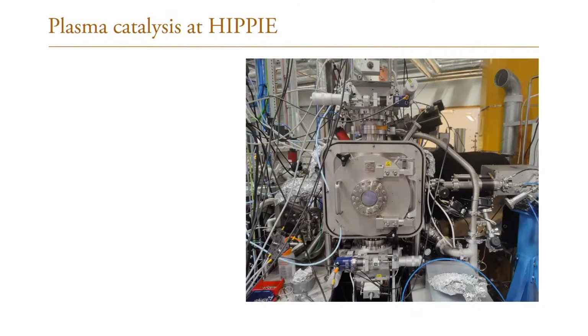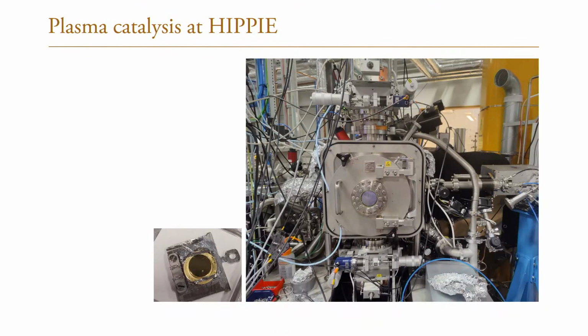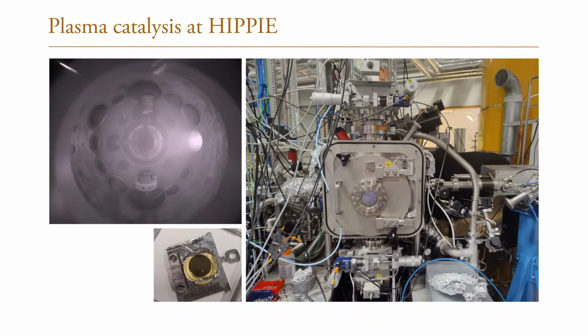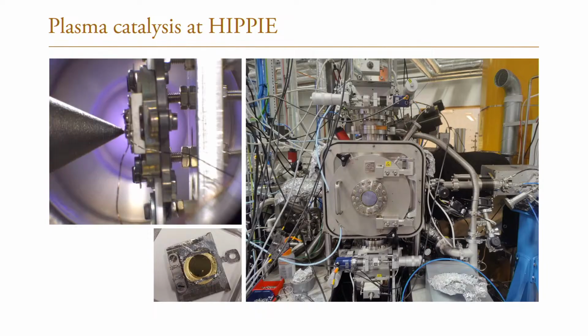So we did the first plasma catalysis experiment at MAX IV, and it's actually the first experiment of its kind ever performed at the synchrotron. So we came up with this idea, and this is the chamber where we put in our catalyst. As you can see, it's slightly light blue in the window there, and that's because there's plasma in there. And also we have our catalyst in there. The catalyst looks like this. In this case, we tried a gold and a nickel catalyst. Inside the chamber, it's a little bit hard to see, but it looks like this. So here is the plasma and the sample is in there.